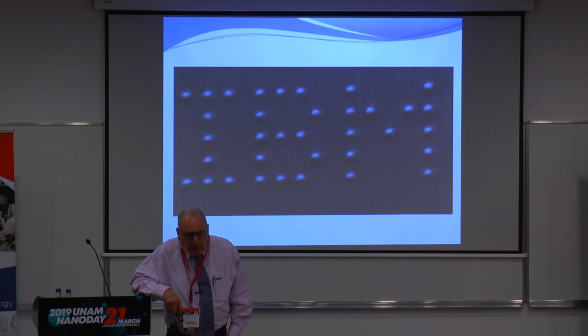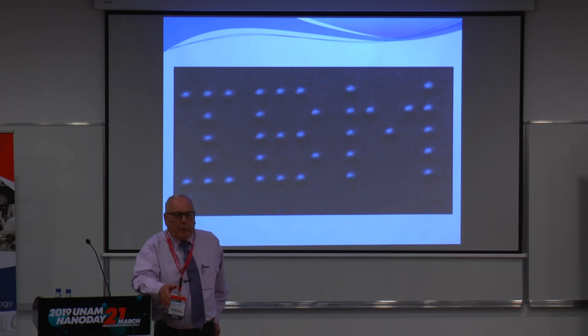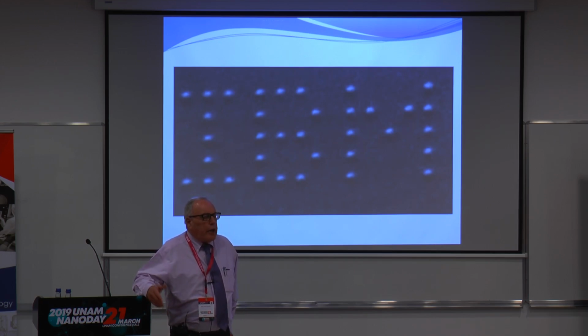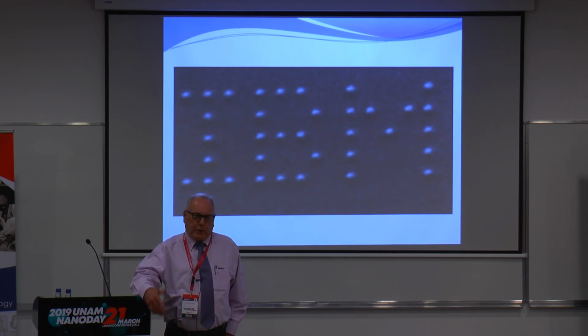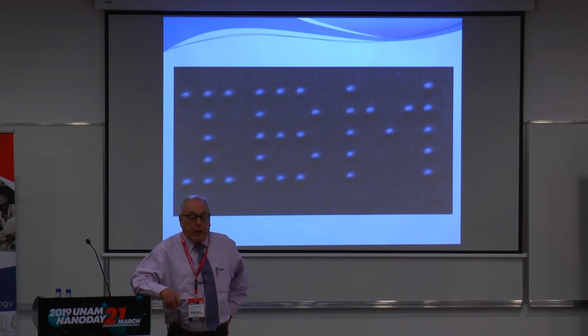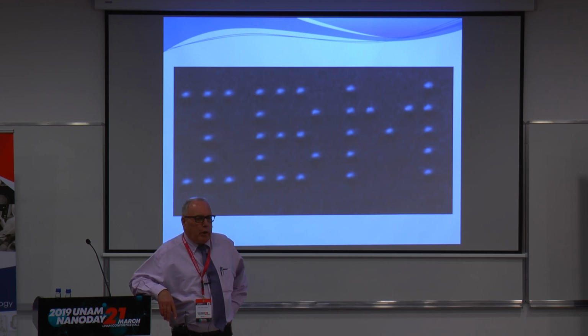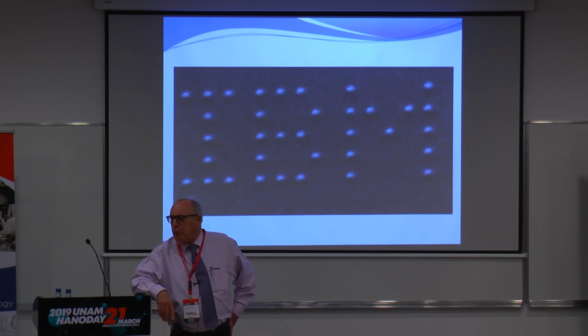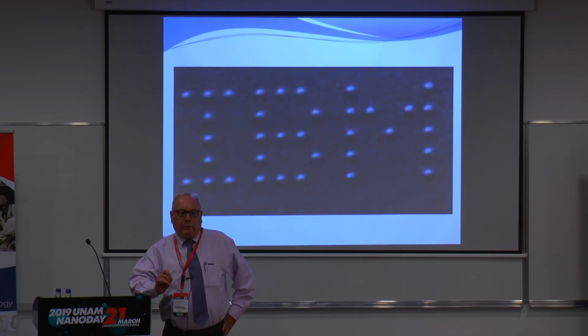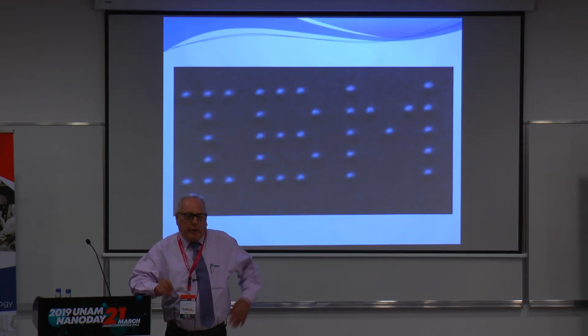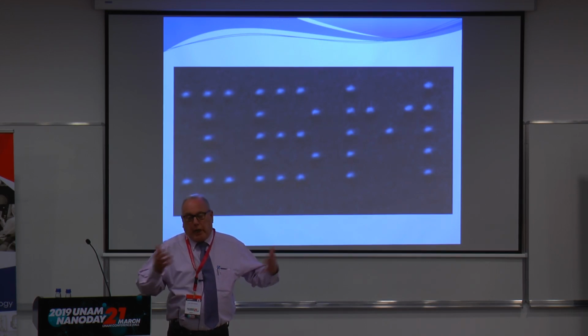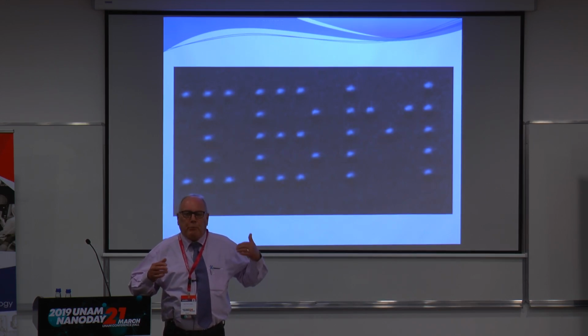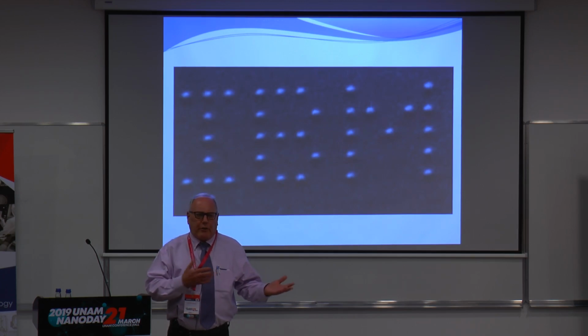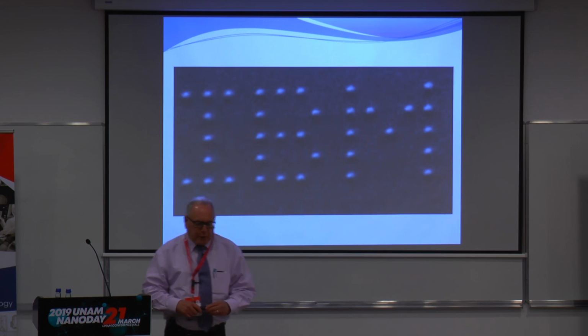And anyway, the important thing about this is that the STM was invented by Binnig and Rohrer at IBM for the purpose of creating accurate images of atomic surfaces down to and including individual atoms. The instrument was very much appreciated that way. And then the atomic force microscope was kind of like the stepson of the STM. But what Eigler and Schweizer did, and their work was built on other people's work from a couple of years before that, was they showed us that the STM could be used not only for making images of atomic surfaces, but in fact altering an atomic surface atom by atom. And some people would say that that's really what nanotech is. I think actually, personally, that nanotech is a lot more than that. But if this is the most dramatic event in the history of nanotech, then some people like to think that the real nanotech begins with the Eigler-Schweizer experiment.